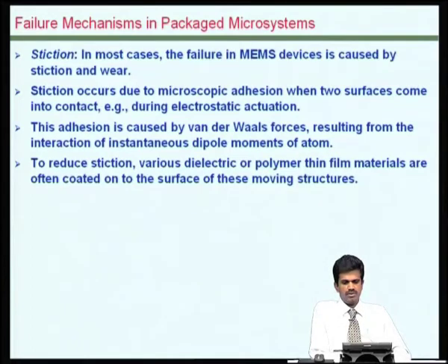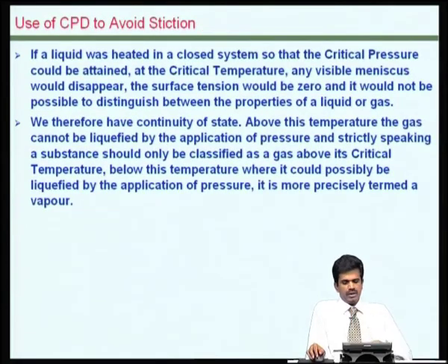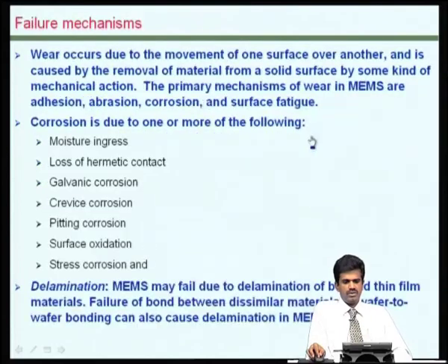In electrostatic actuation, you may recall we have a beam which is pulled down by applying a potential. So, when this beam touches the surface of a conductor beneath, if both of these are planar surfaces, these may adhere due to the van der Waals forces, and this can result in these sticking together. To some extent, this can be limited by using a dielectric layer above the conductor, and there are various other approaches of minimizing stiction. If you recall, during the fabrication stage also stiction is an issue in surface micromachined devices. Critical point dryers could be used to avoid stiction in that context.